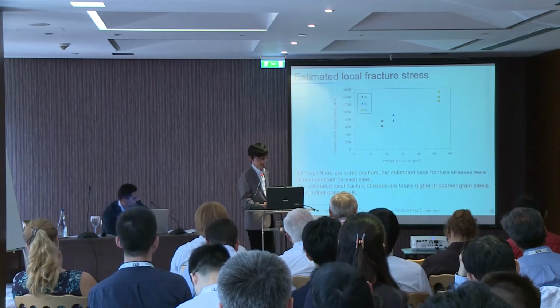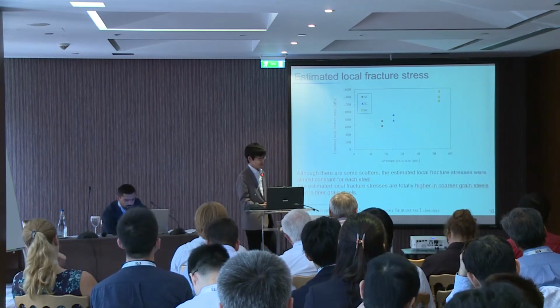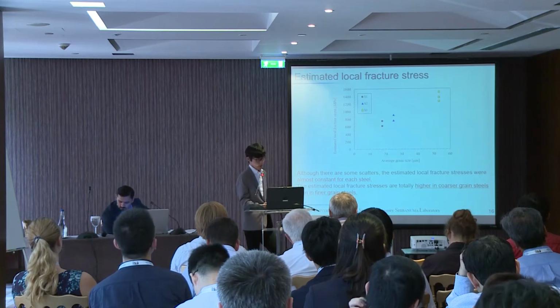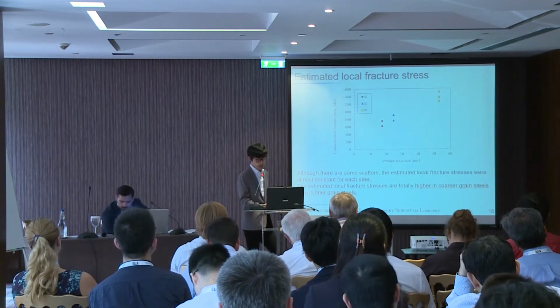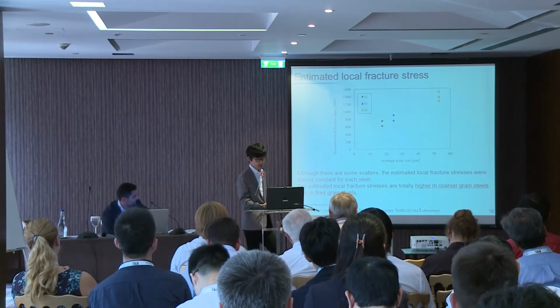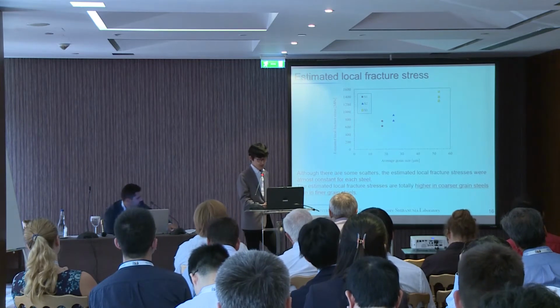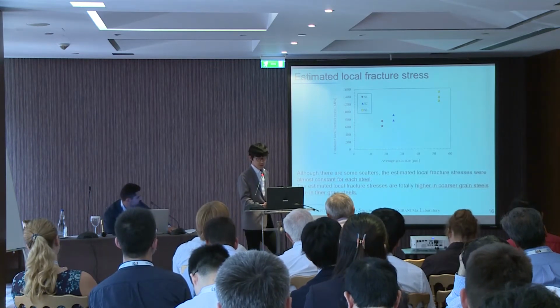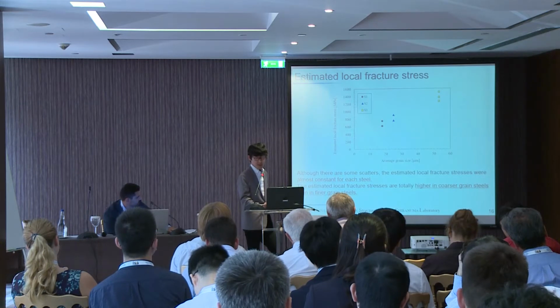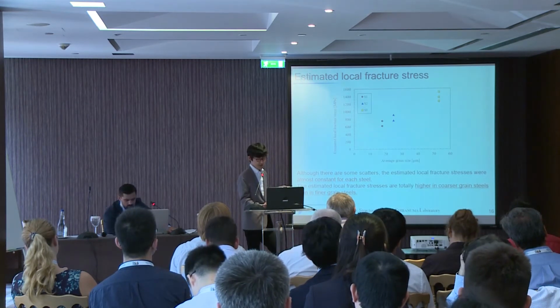The result of estimation of local fracture stress for each steel is this graph. Although there are some scatters, the estimated local fracture stresses were almost constant for each steel. The estimated local fracture stresses are totally higher in coarser grain steels than in finer grain steels.